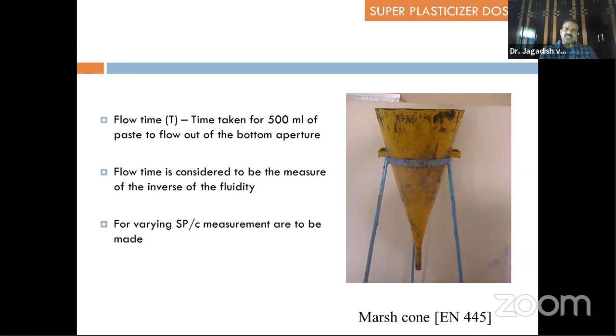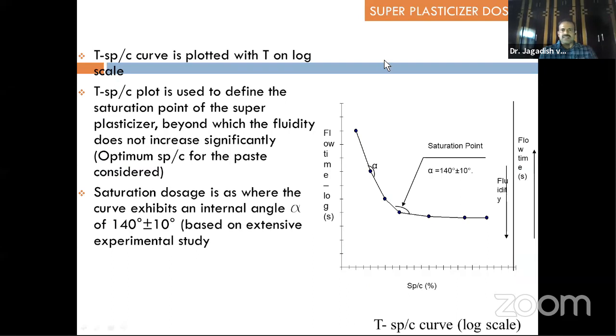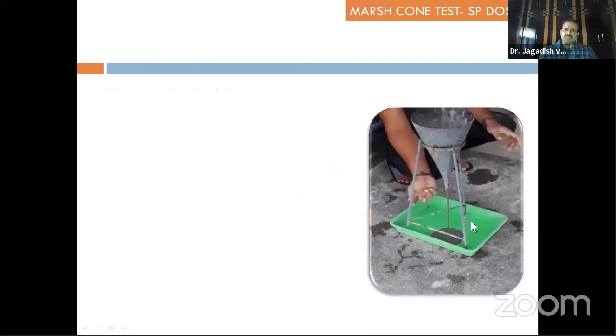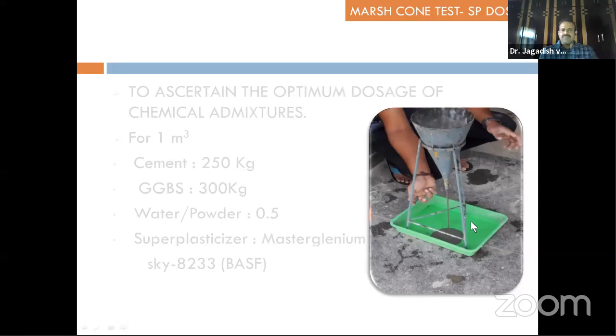So flow time versus superplasticizer dosage. You will get a curve like this. After a certain point, even though you add more superplasticizer, there won't be any change in flow time. Typically, this saturation point is 140 plus or minus 10. You can see that. So these are some of the experiments conducted at our earlier college, BMSIT, with our students. You can see the marsh cone wherein we have placed the mortar and then measured the flow time.